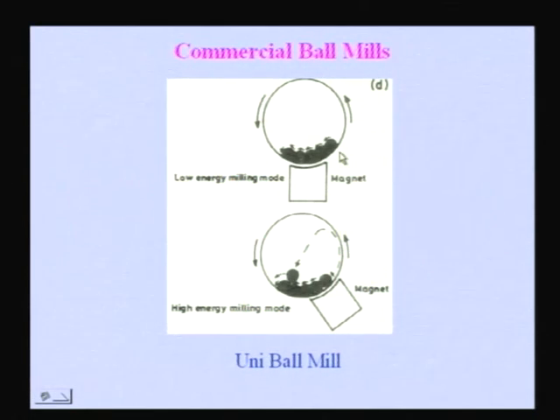So, one can control the mode of energy transfer, whether it is just shear or an impact kind of energy. So, one can change this energy mode by changing the position of the magnet, and that is why we call this a low energy mode and a high energy mode. So, if you put the magnet at some position somewhere here, let us say, you will get much higher energy. So, like that one can control this, either shear mode or the impact mode. So, here also one can produce large quantities, at least about 5 kilos or so. So, these are the typical types of mills that we use.